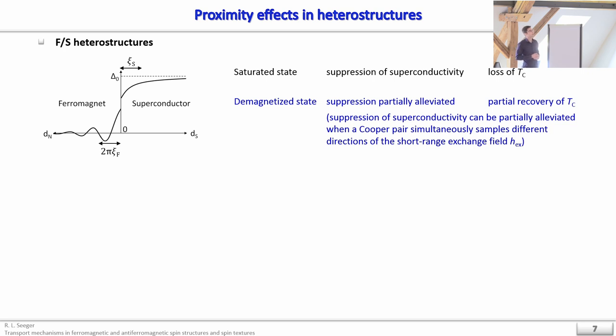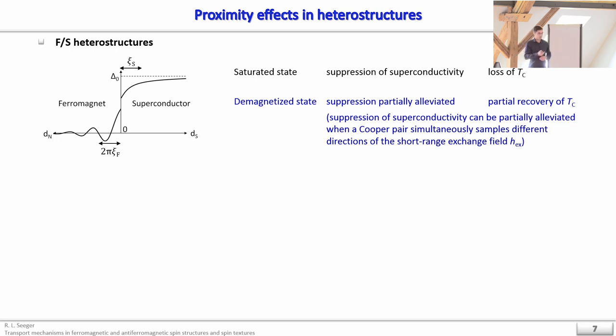When the adjacent material is a ferromagnet, different situations arise. If the ferromagnet is in its saturated state, you expect suppression of superconductivity because Cooper pairs feel a homogeneous exchange field, leading to Cooper pair breaking and a decrease in critical temperature compared to the bare superconducting layer. On the other hand, in a demagnetized state with domain walls, the exchange field rotates and on average the field sampled by the Cooper pairs is reduced, partially recovering the critical temperature.